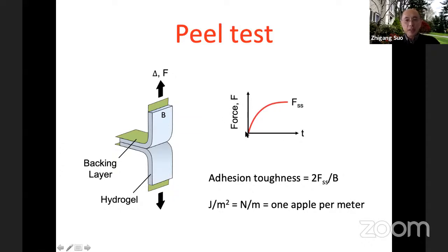So initially, this crack does not grow, you just get a blunting. So you add more force, you get blunted more, and then at some point it starts growing. When it starts to grow, it reaches a steady state.